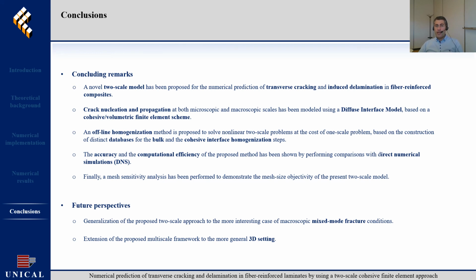In conclusion, a novel two-scale model has been presented, able to accurately predict transverse cracking and induced delamination in fiber-reinforced composite materials. This model adopts an inter-element cohesive finite element methodology for the numerical simulation of multiple cracking at both micro and macro scales. As the main ingredient of the proposed two-scale model, a very efficient offline homogenization approach is introduced for the bulk and cohesive interface constitutive behaviors.